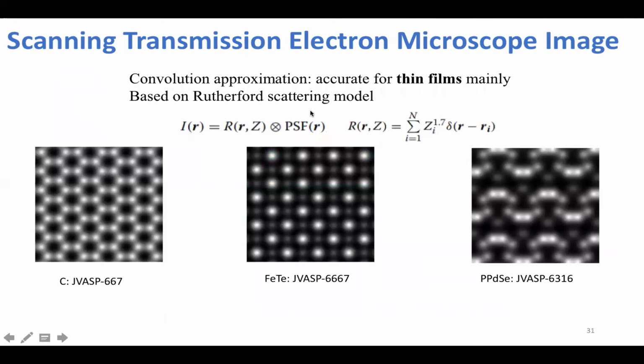Similarly with STEM, we use the convolution approximation, which is a basic approximation that can be used for thin films such as 2D materials. The convolution approximation is based on the Rutherford model of scattering, where the intensity of scattering is proportional to Z squared. But because there are a lot of other losses, we use an exponent of 1.7 or 1.4. Using this model, we can simulate STEM images of 2D materials.